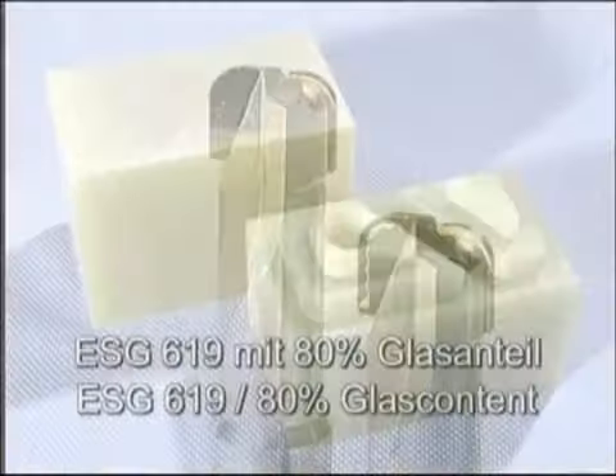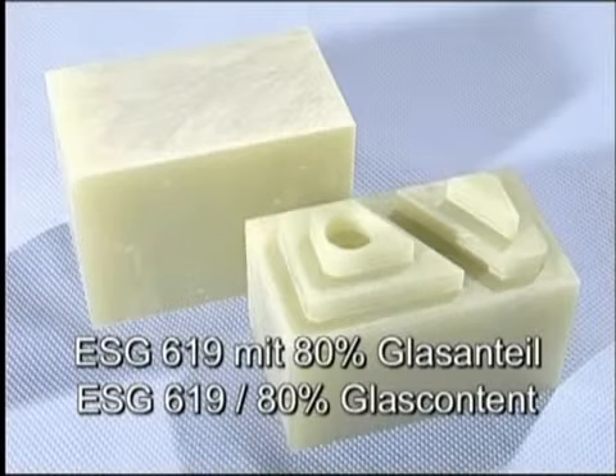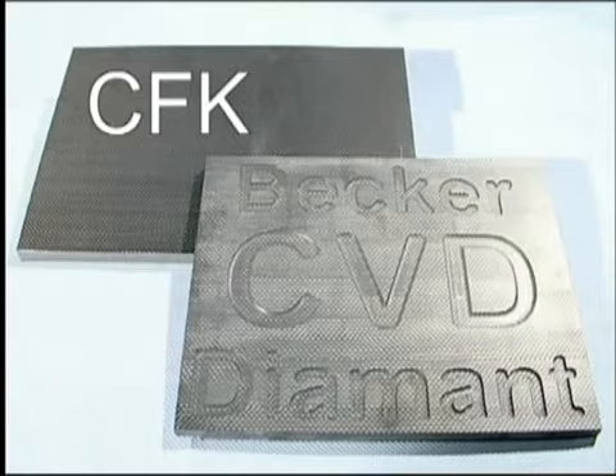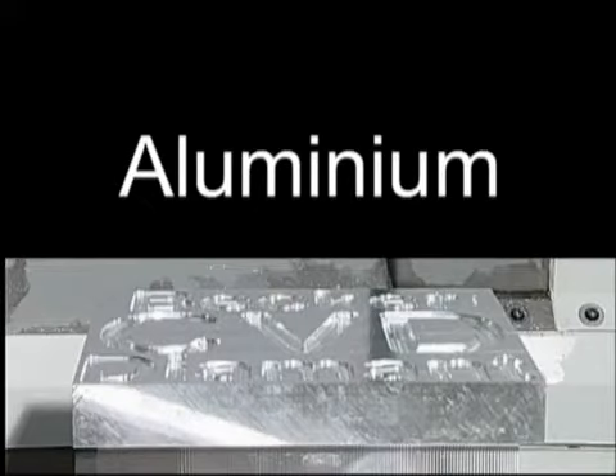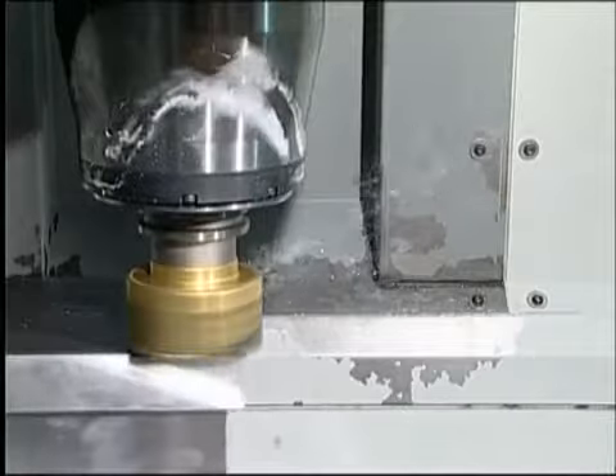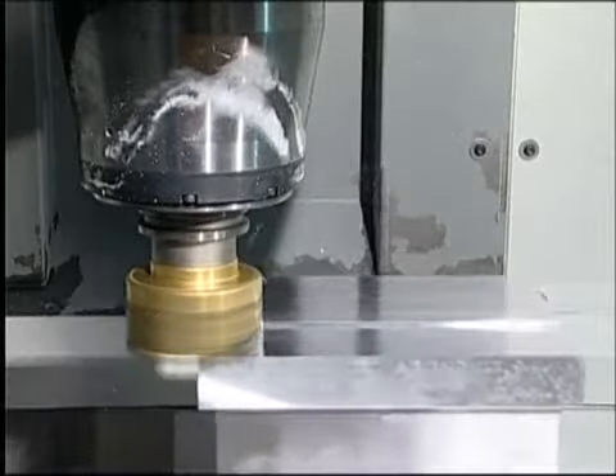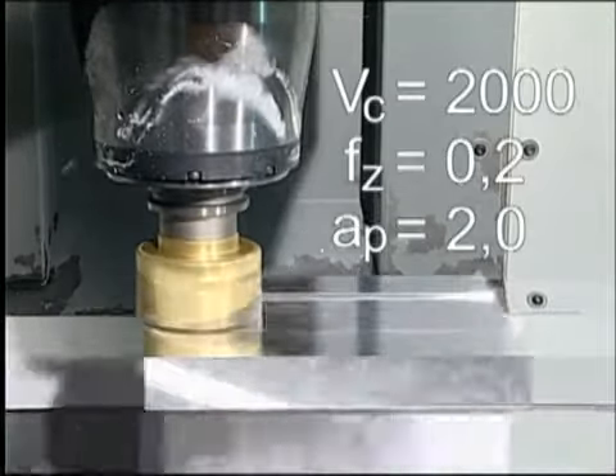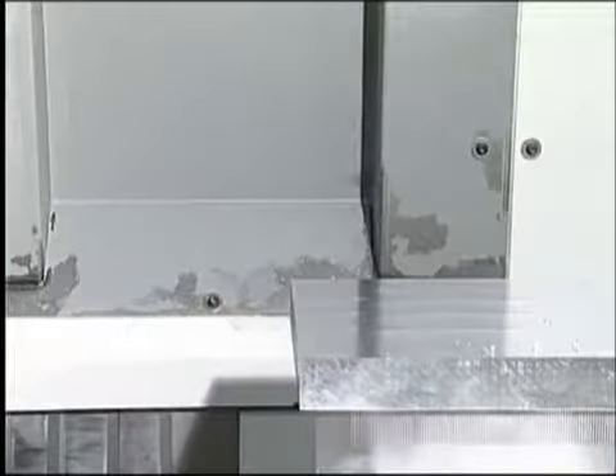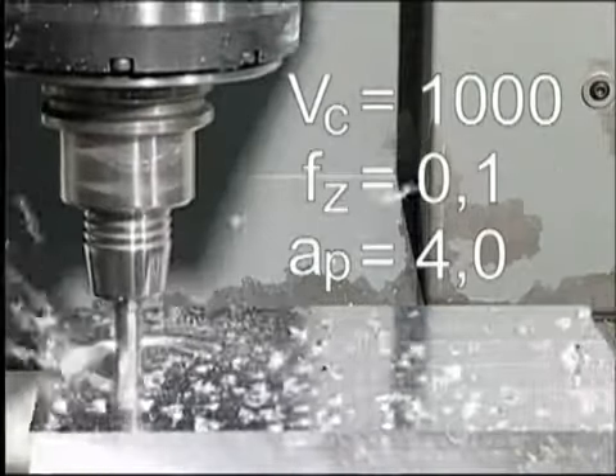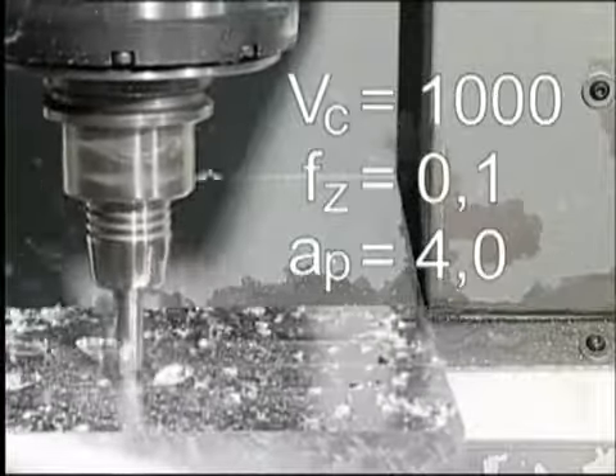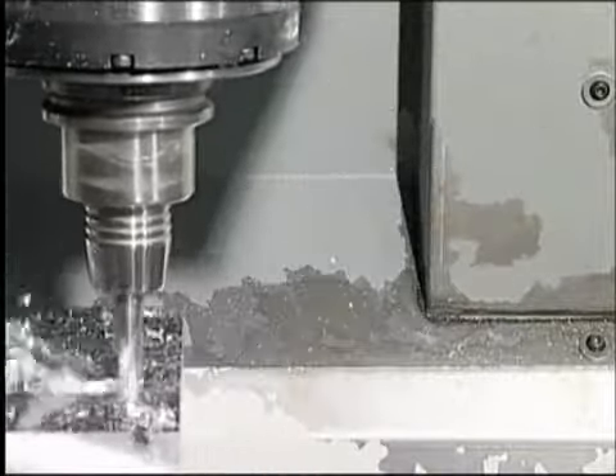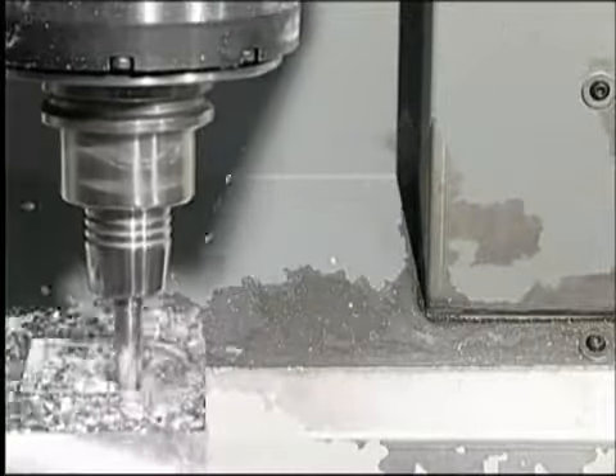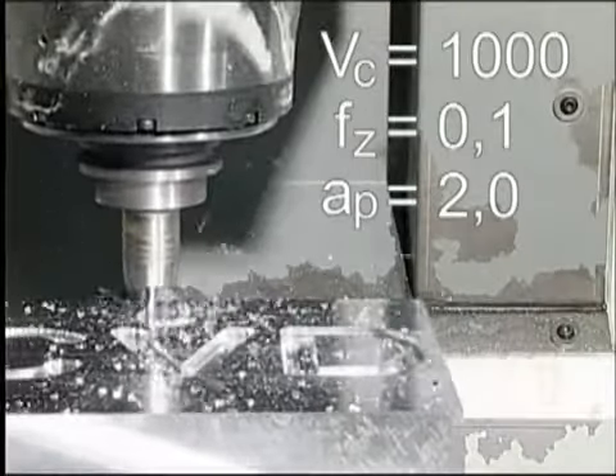We will demonstrate the dry machining of materials that are extremely difficult to machine. We will start with an aluminium that is a very abrasive material due to the high silicon content. There are many alloys that even PCD cannot economically machine. Using Becker CVD diamond tipping, we can increase tool life up to 3 to 6 times in comparison to conventional PCD.